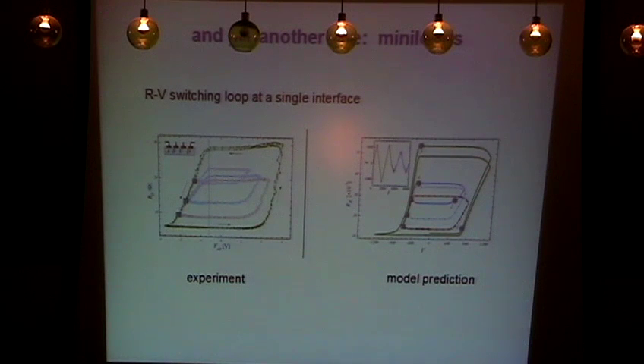Isn't it that at the interfaces, the ion concentration and the electron concentration are decoupled? So what you're saying is like it's kind of a local electroneutrality assumption, that if I change the ion concentration, I also change the electron concentration, right? Because you have to somehow couple the concentration change in the ions with the change in the resistance. So you have to couple the ionic system with the electronic system. Sure, the more, yeah, but it is not always.